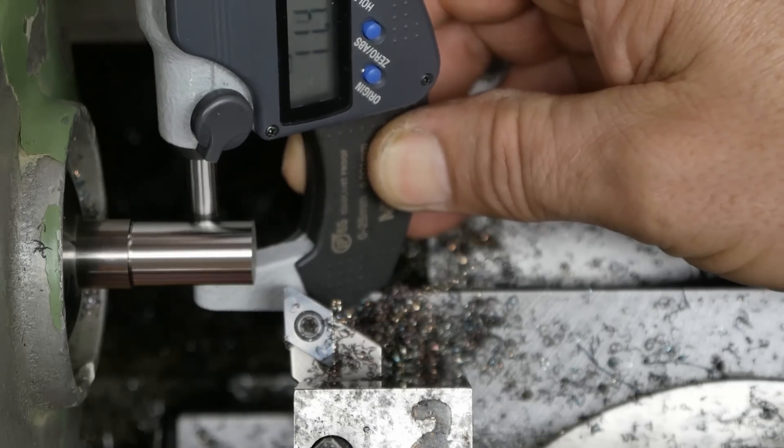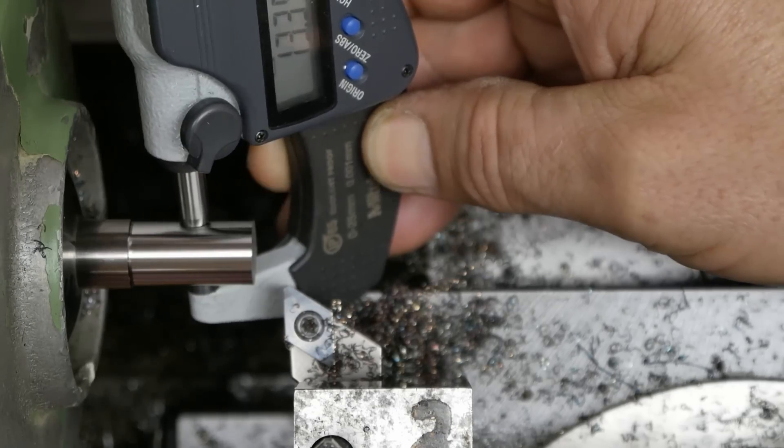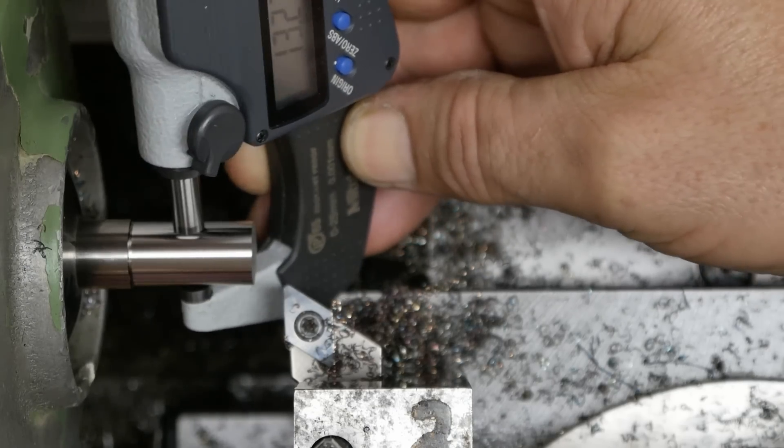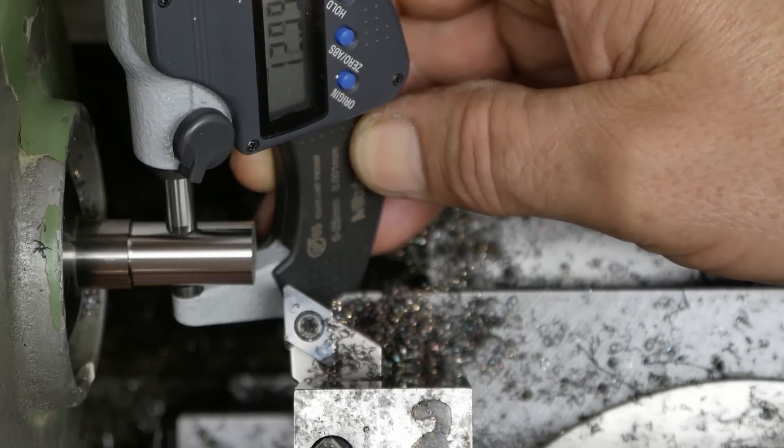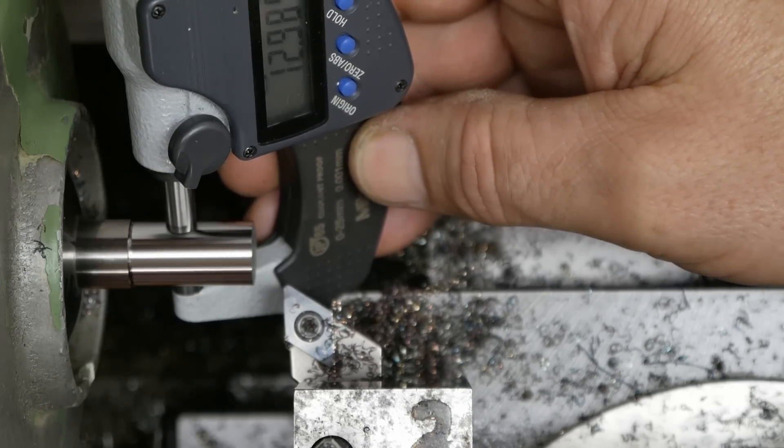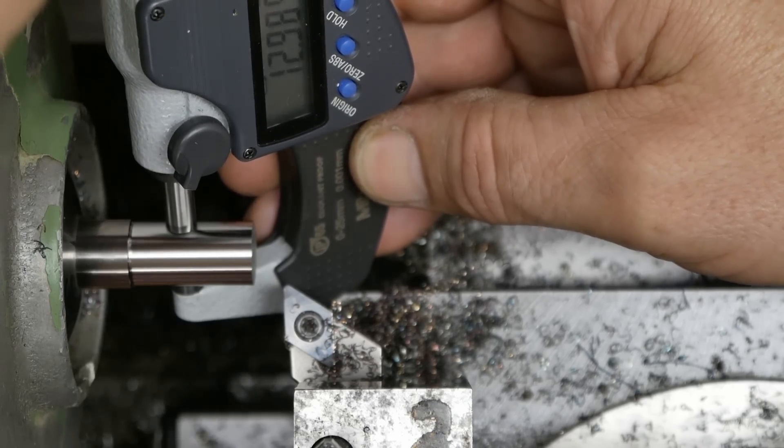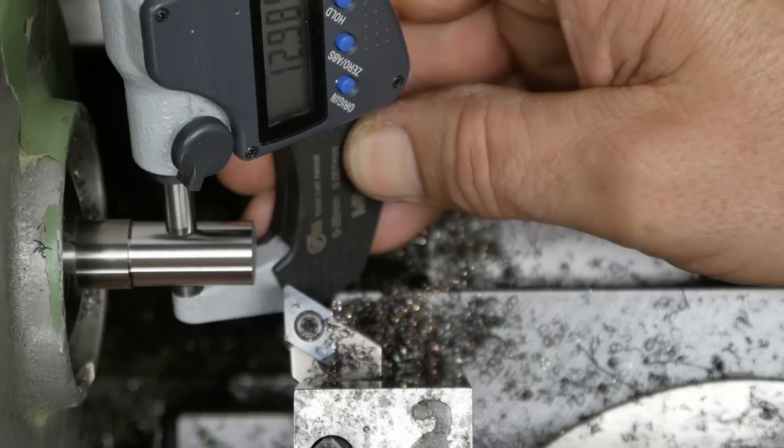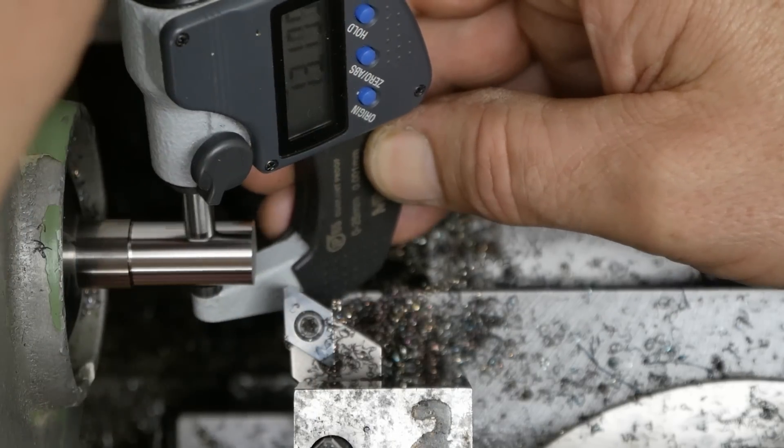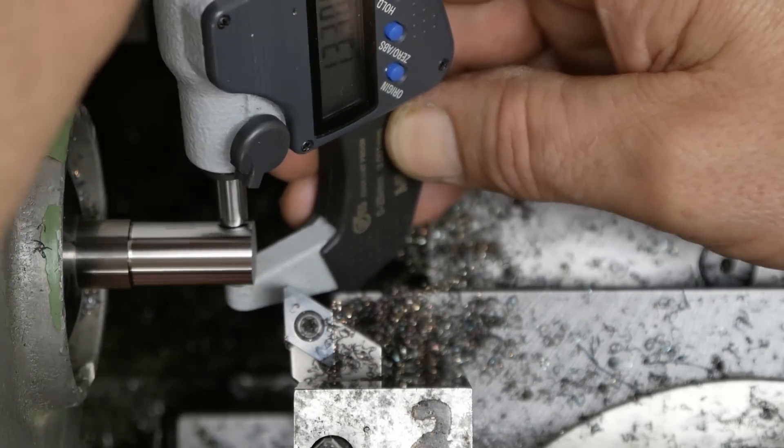All right. Well, that's what you get a Schaublin for, huh? Man, that surface finish looks amazing. Just to answer the comment there, am I using constant surface speed mode? Yes I am, so you might have heard it slightly speed up between each pass. I mean, they're only, the increments are only 0.15 of a millimeter. That's probably on the low side of the acceptable range of cut for these inserts. I wanted to be conservative at the start. At this diameter we got up to about 2800 RPM, and it'll be probably about 3100 once it gets down to the 10 millimeters.